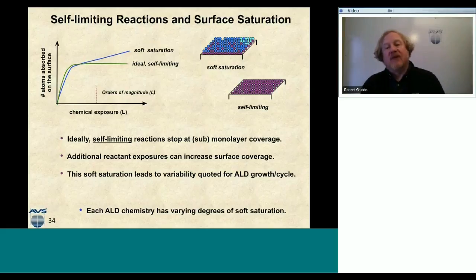So I've tried to sort of identify those in these cartoons I've shown on the right. So this soft saturation can lead to variability in the quoted ALD growth rates per cycle. And ALD chemistry even has varying degrees of this soft saturation. Alumina being our most ideal ALD chemistry, even that will show a little soft saturation if I really hammer that surface with a lot of chemical precursor.